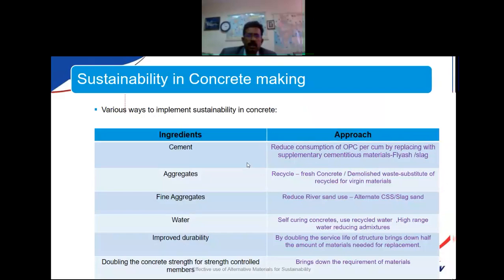So already I've discussed these points, cement. The replacements for OPC cement, in reducing the carbon footprint, are slag and fly ash, the main replacements. But of late, they are using calcined clay to make cement. That's also there. And at the higher end for high performance concretes, we are using ultrafine materials. For aggregates, we are using demolished waste as a substitute. Up to 25% is allowed as per IS codes. There are certain countries which are using up to 50% replacement of virgin aggregates with recycled aggregates.